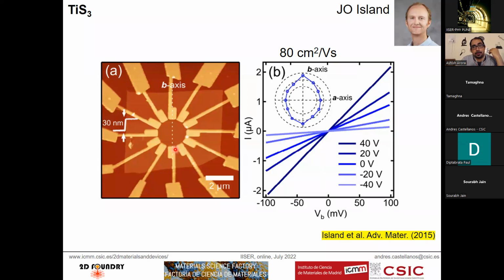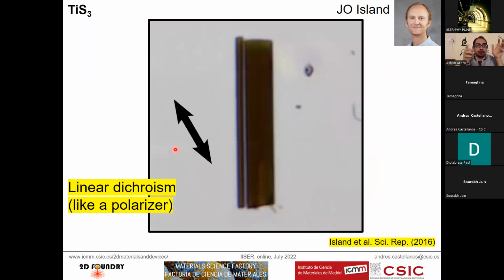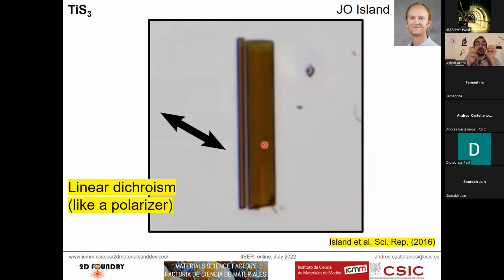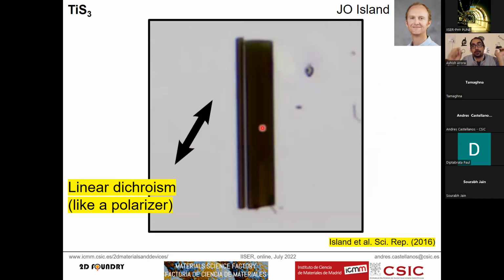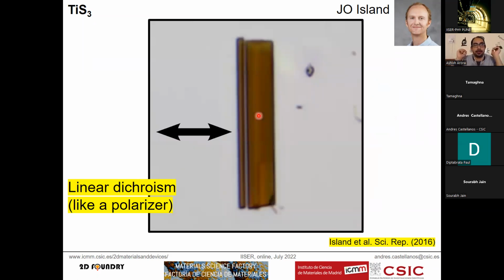But I think we have not carried out polarization-resolved transmittance measurements. Because this looked very interesting. One slide back. What was the channel here? Was it red, green, or blue? I mean, was it one of the channels, or was it complete broadband? No, this is complete broadband. So that's why it becomes brownish. Oh, this looks very interesting then. I mean, the band edge shifts appreciably when changing the polarization.